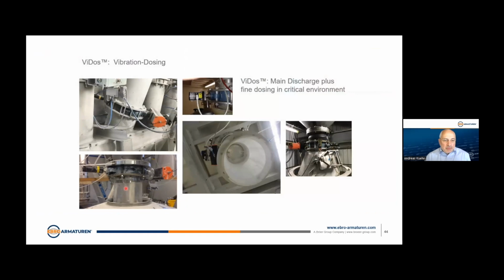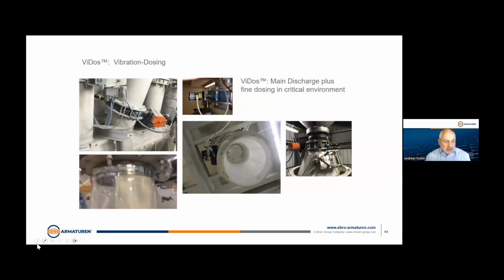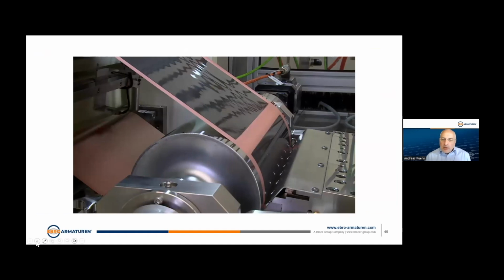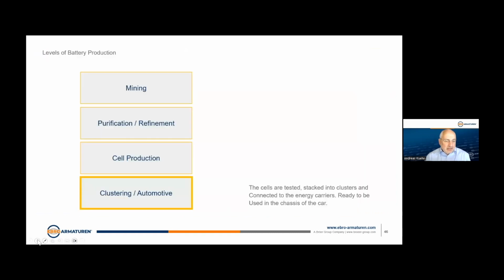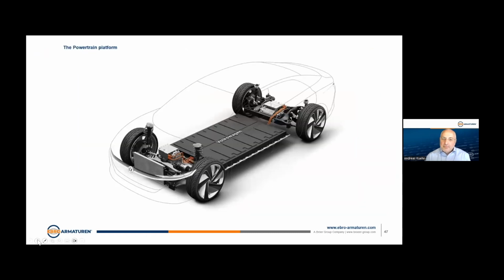Some samples here. So even if you close down the valve down to, let's say, 20 degrees opening angle, the vibrator makes sure that the material is still running, even if it is a very complicated material. So we just learned, we have the copper foil, we have the aluminum foil, we bring on the slurry, we dry it, we cut it off, and the battery cell is then produced and clustered. And that's the end of the line of the production.